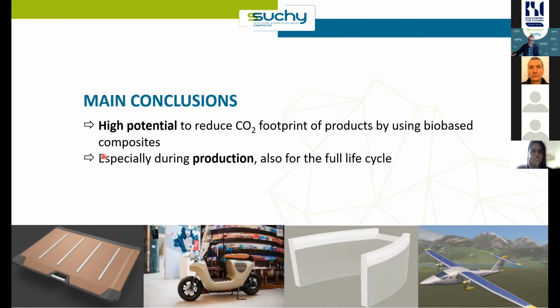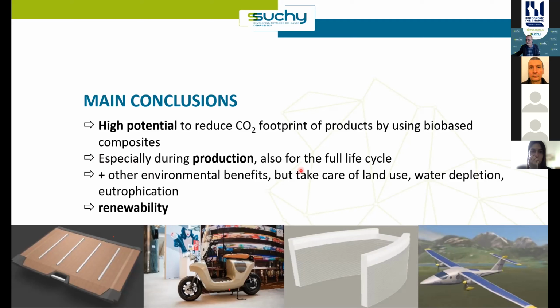For the full life cycle, there we also have the impact of the energy consumption in mobility that lowers a bit, and we also have these end of life scenarios that lower a bit the entire benefits that we had with the production, but it's still beneficial in terms of CO2 emissions. We also look at other environmental benefits, and we all know that if you go to bio-based materials, you also have to carefully look at the land use you need for it, and water depletion, although I can say that this is not larger than in the benchmark solutions if we use the hemp, and eutrophication.